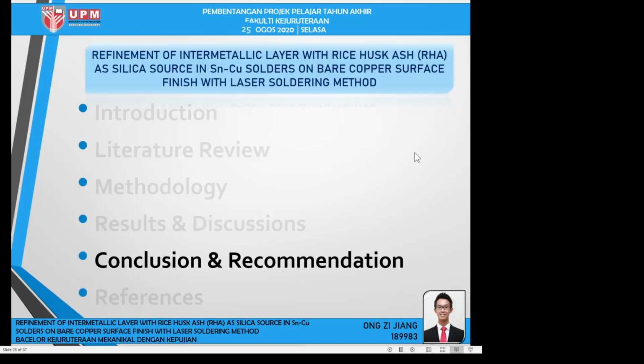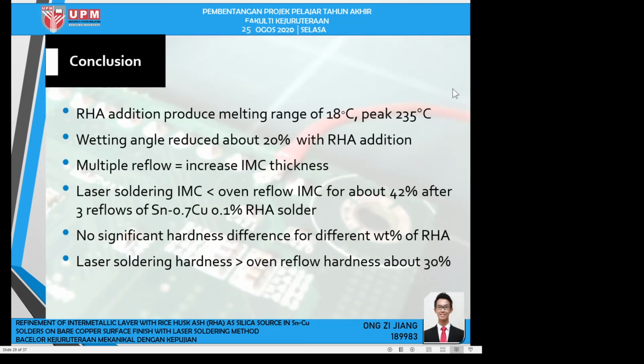So here comes the conclusion and recommendation. In conclusion, RHA addition produces a melting range of 18 degrees Celsius and a peak temperature of 235 degrees Celsius. And the wetting angle has been reduced about 20% with the RHA addition. Furthermore, multiple reflow for sure will increase the IMC thickness, but in our study, the laser soldering IMC is much thinner than the oven reflow IMC, by about 42% after 3 reflows.